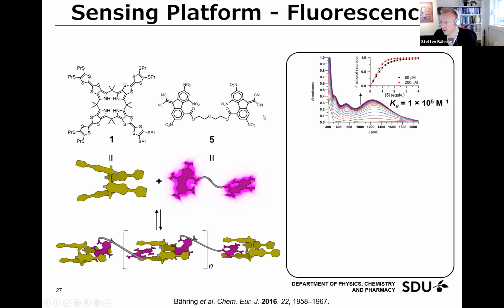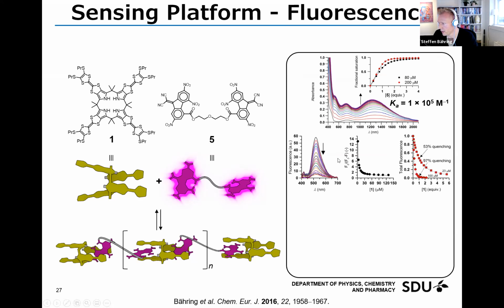But this fluorenone derivative was also fluorescent. So we thought that we might be able to exploit this in an indicator displacement type assay, where we could first quench the fluorescence when we make the one-to-one stoichiometric supramolecular polymer. And here you can see that at different concentrations, we're exploiting the supramolecular interaction. So at 80 micromolar of total both monomers, we had 53% quenching.